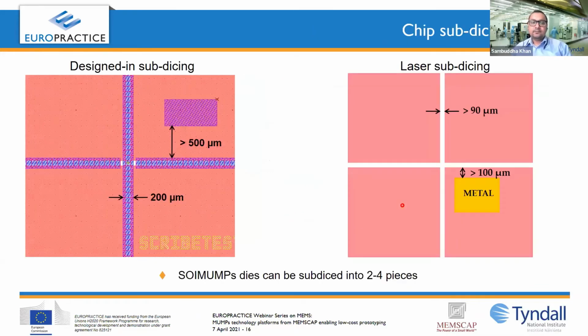There are options of chip subdicing. Once the device is processed, you can subdice it. There are two ways of doing it. One is laser subdicing, one is designed in subdicing. Designed in subdicing means in the mask layout, you have to define the dicing lines, and dicing lines in all the layers. That means in the trench layer, you have to define a trench. So you can see the white at the background, that is for the trench. So that is the trench mask. That means the substrate needs to be removed from this area, as well as from this area and this area. You have to remove the entire substrate from there.